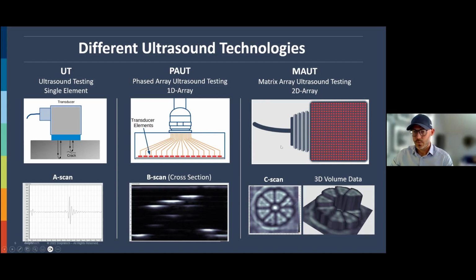So the next step, what we've done is a 2D array. So we have elements in both directions, both X and Y. So we're introducing another dimension. And then in addition to the A scan and the B scan, which I will show you later, we now have what we call a C scan, which is a cross section the other way in the planar field. So that makes it incredibly intuitive. It's kind of like looking through your transducer, and you can see this, similar to an X-ray picture. And it's much more intuitive to interpret. So that's the travel through basic UT to phased array UT, which is a 1D array, and then to our 2D array.